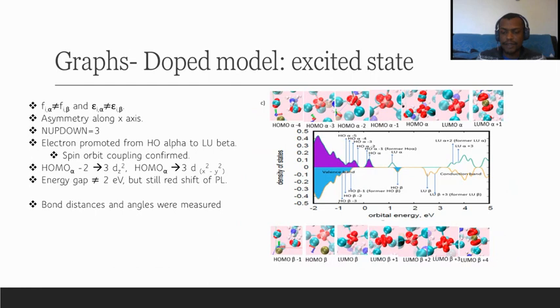So in the excited state, after we plotted the spin polarized density of states, we can see the spin flip, which can be seen here, that we have an electron in the HOMO beta, right? That's the transition between the HOMO alpha to the LUMO beta, the previous one.